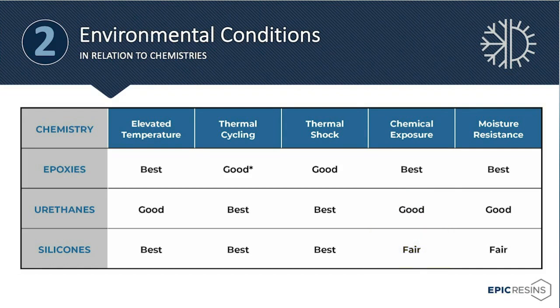When we're comparing moisture resistance for epoxies, urethanes, and silicones, epoxies really have the best moisture resistance, again, stemming from epoxy's ability to have high cross-link densities. High cross-link density is essentially going to be blocking the moisture from impregnating the polymer. Urethanes don't have quite as good as epoxies. Again, that's stemming from their little bit lower cross-link density, not quite as high of a TG ability, whereas silicones are fair because they do have a fair amount of ability to be attacked by moisture.